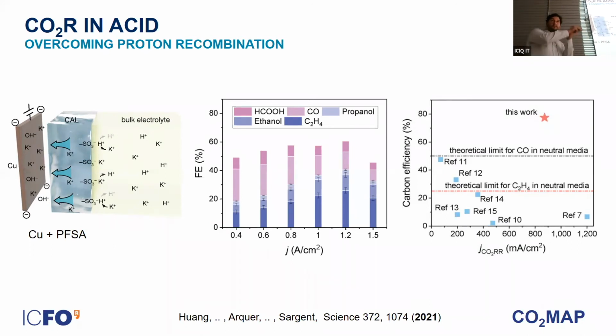So the local population of potassium ions at the surface of copper would be much higher than otherwise, because the solubility of potassium ions would be limited in water. You have kind of a solid environment where potassium is more available. You can see in this way how, by using this new catalyst and screening the current densities, we can be more productive. Focusing on this regime, for example, we could generate CO, an amount of ethylene around 20% at around 1 ampere, and even we could see some propanol.